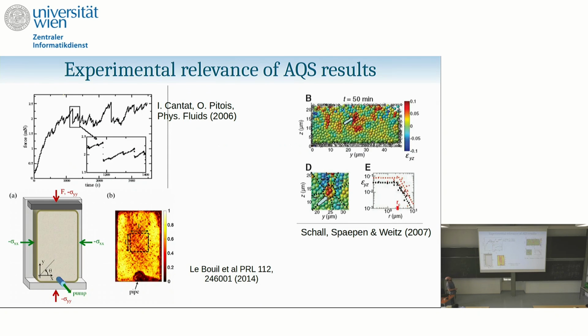I will just show this, because it shows that the connection with experiments matters. First, I love this. This was a paper on foams, where people were accessing the quasi-static regime in sheared foams. This is a paper by Peter Schall and others, where they were also looking at these HLB events and at the local strain, and they have indication of the HLB field. And that's a more recent paper where people look at strain in a granular medium, and they find indication of HLB-type correlations before the formation of shear bands.